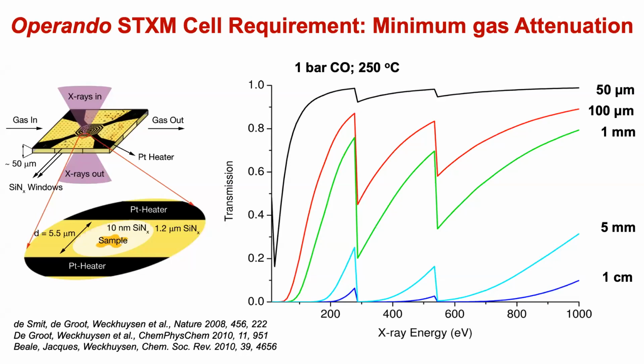So if you take 1 bar of CO at 250 degrees C, you can see here, if you have 2 plates, how far are they from each other? And you can still have transmission through the system. And you notice that you have to bring the cell to the 2 windows, which are actually silicon nitride windows in this case. If you want to measure carbon, you have to bring them about 50 micrometer apart. That's not a lot. And there you have to put your catalyst particle in between.